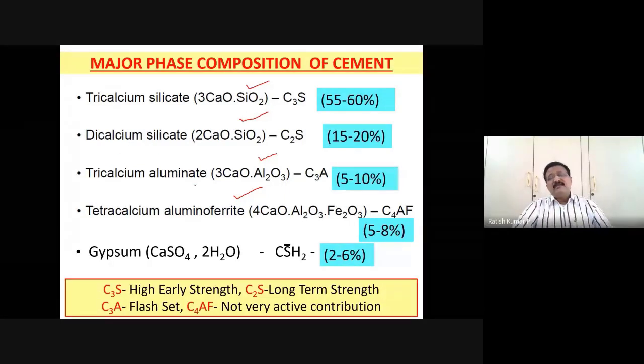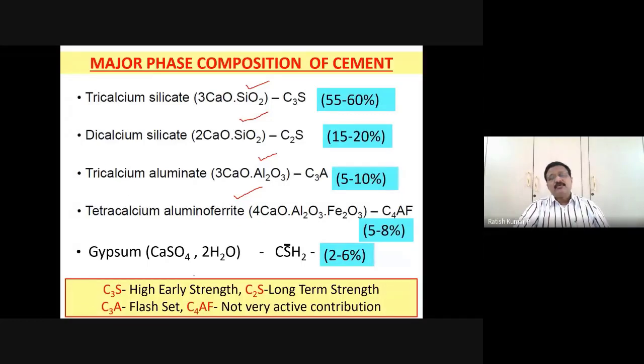Now the gypsum is there, which is in very small quantities, as I was trying to point out. And then the advantage we are also going to get is by probably adding certain calcium carbonate as a performance additive. We can think of ways and means of increasing this performance additive from 5% to something like 10% or so, so that the calcium carbonate, when I use it at the grinding level, I'm not going to heat it. So obviously the carbon dioxide emission is not going to be there. So that sort of valorization can definitely be useful.